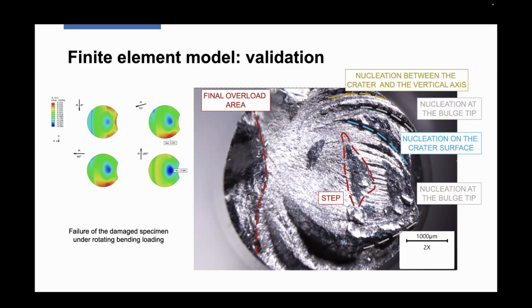What we can observe is this area where there is a step discontinuity. This area, according to our finite element results, is subjected to compression during the whole loading cycle. So the appearance of the discontinuity can be due to the resistance provided by this area of compression. There is a time in which this area is surrounded by tensile stresses, and so the discontinuity appears.